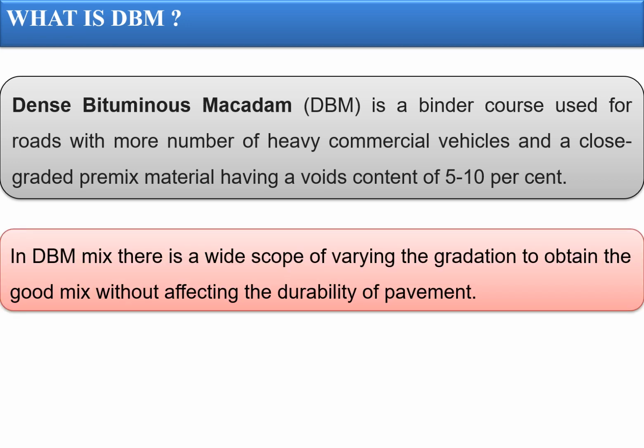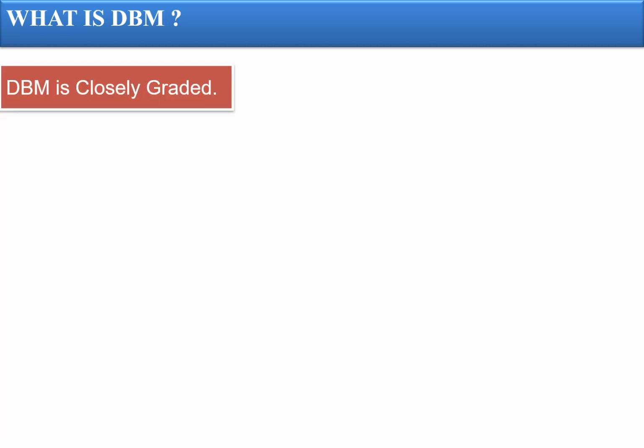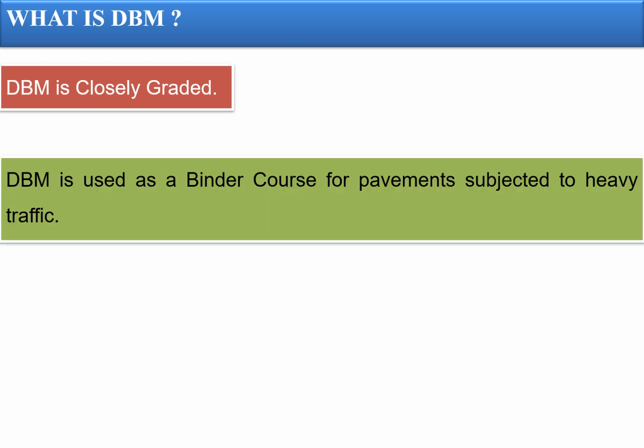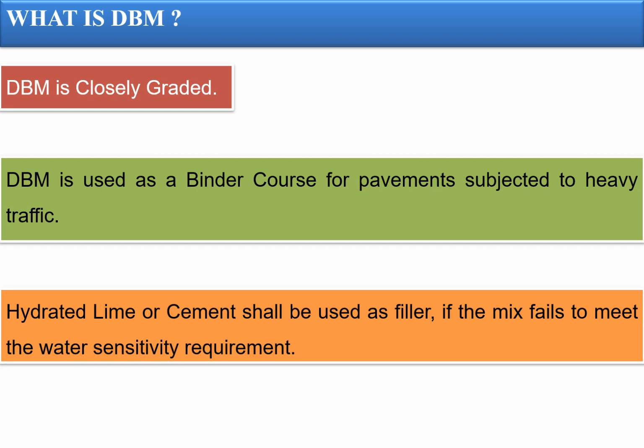In DBM mix, there is a wide scope of varying the gradation to obtain a good mix without affecting the durability of the pavement. So we can say that DBM is a closely graded mix used as a binder course for pavements subjected to heavy traffic, and hydrated lime or cement is used as filler if the mix fails to meet the water sensitivity requirements.